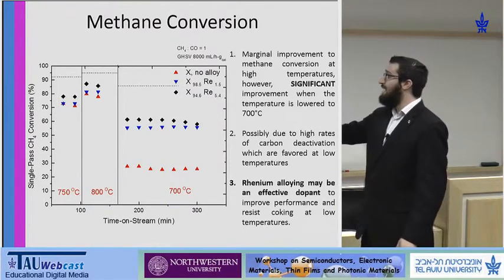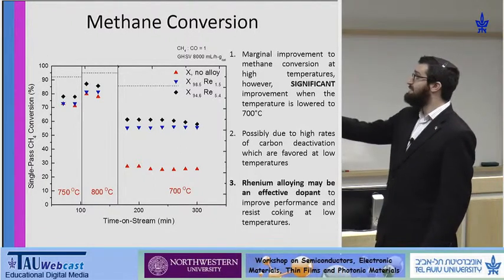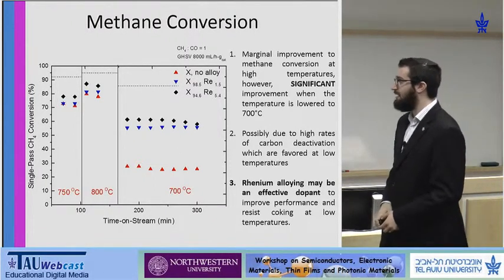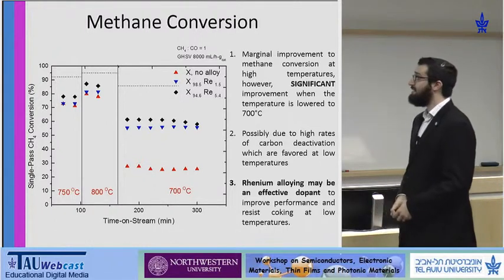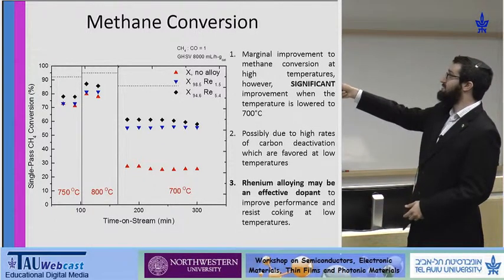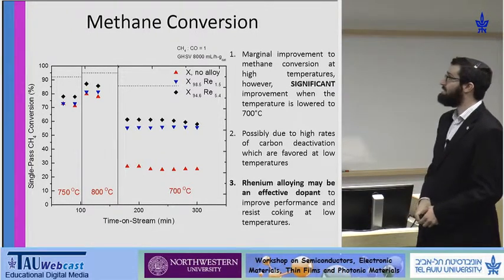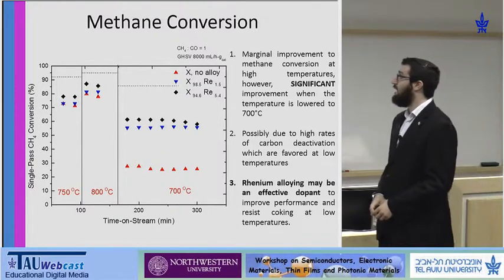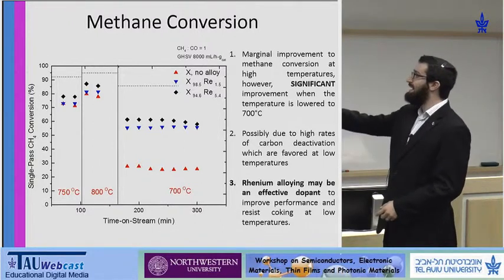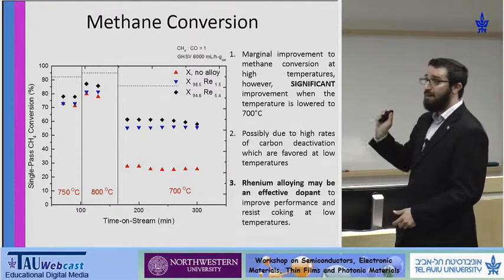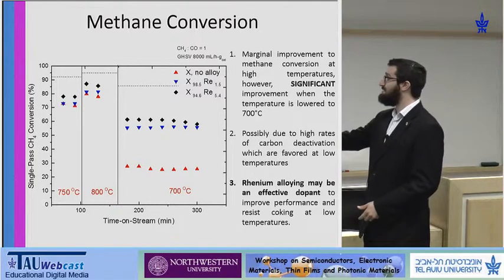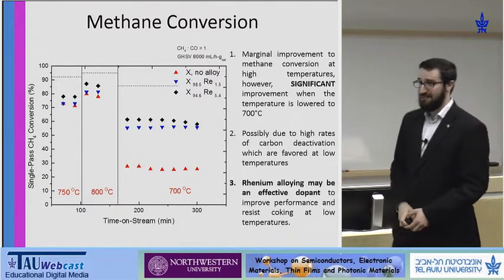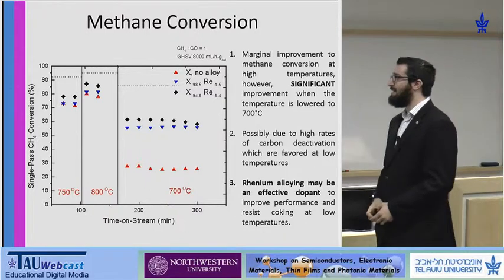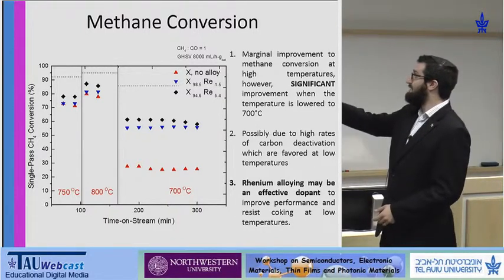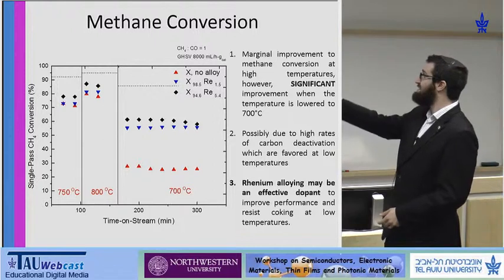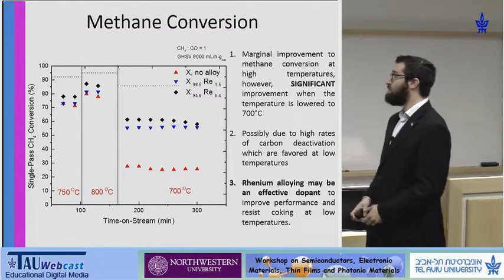So for example, at 750 degrees C, we see only a marginally higher contribution for methane conversion when we alloy the catalyst with either 1.5% or 5.4% atomic, of course, rhenium into the film. And again, at 800, only these marginal differences. But when the temperature is reduced to 700 degrees C, we see a significant change in the methane conversion. The unalloyed catalyst is down at around 30%, and the alloyed catalyst is about twice that.